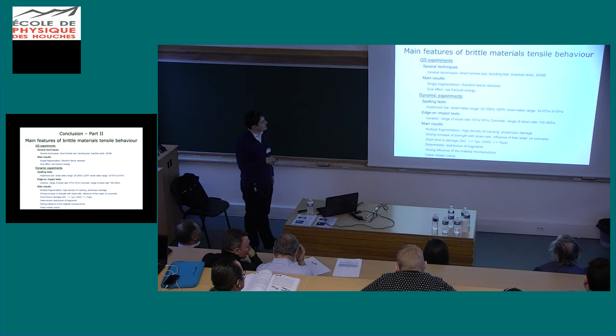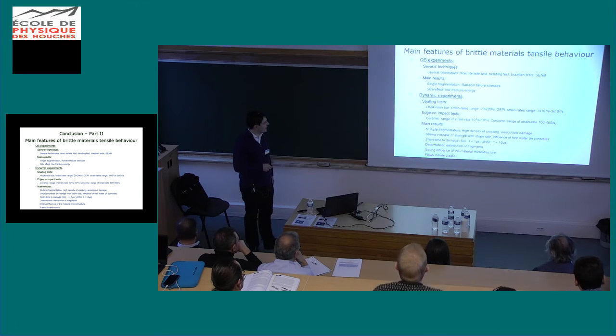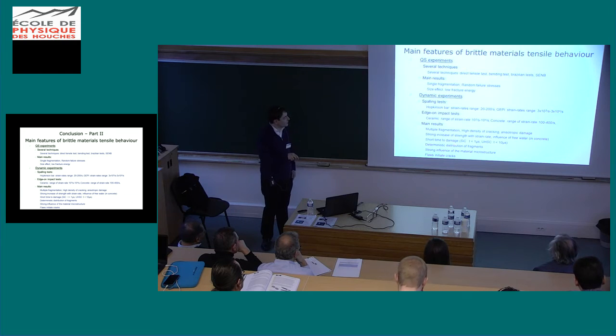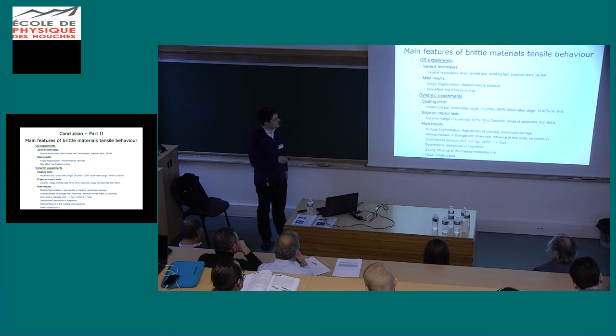Under dynamic experiments, a split Hopkinson bar can be used in this range, and other techniques are needed above 1000 s⁻¹. Edge-on impact tests can also be performed to visualize damage. And finally, we observe multiple fragmentation, a high density of cracking, a strong increase of strength with strain rate, and a strong influence of free water in concrete, but maybe also in rocks, because rocks could also be saturated with